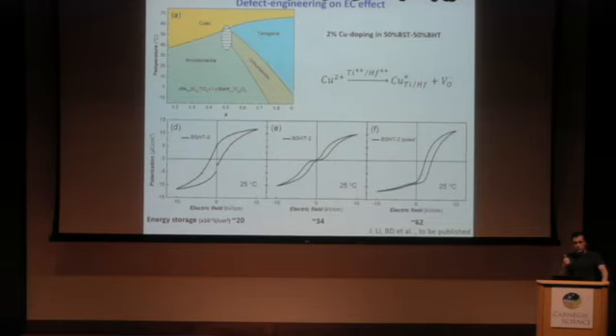Actually, what we did in that case, we also measured directly the thing, and it corresponds rather well with the value that we measured here. And we do think, indeed, that it's because of this pinched curve. You see, once again, you have P max. Let's say you start without an electric field, it's zero, on average, of course. But once you apply the electric field, you can change the polarization a lot, compared to the ferroelectric one. And this is the reason.